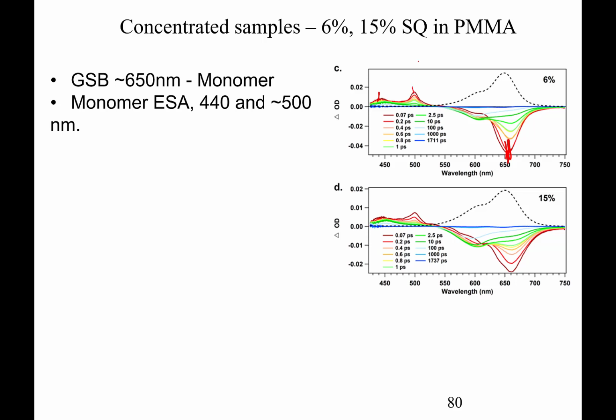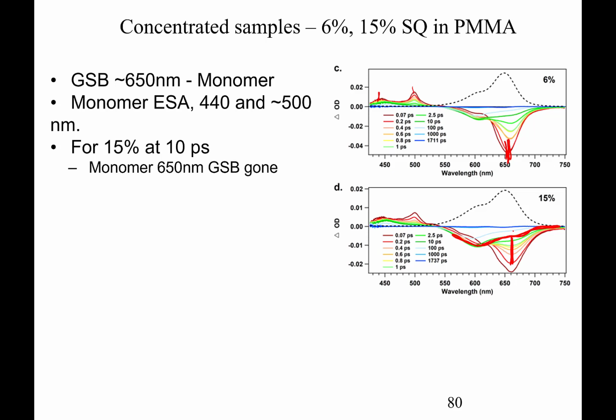So for 15% at 10 picoseconds, already the monomer is completely gone. So we're down in here at 10 picoseconds. We're looking at the green spectrum in here, right? So we're looking right in here, okay? And we're seeing that this monomer ground state bleach has gone. We're also recognizing that there's no more excited state absorption at 500 nanometers. All gone.